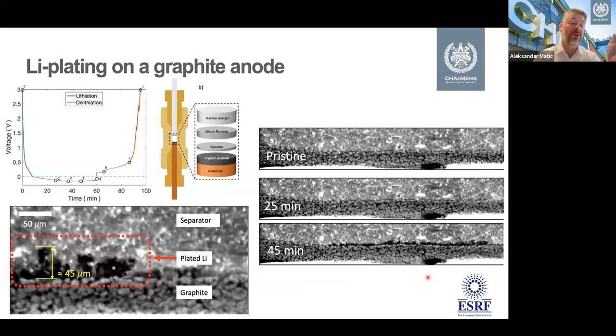But if you, for instance, have too low temperature or charge your cell too fast, you might plate metallic lithium. So you might deposit metallic lithium on the graphite anode or between the graphite particles instead of allowing time for the particles to enter. So we built this special cell here and could in real time take 3D images as the cell was cycled.